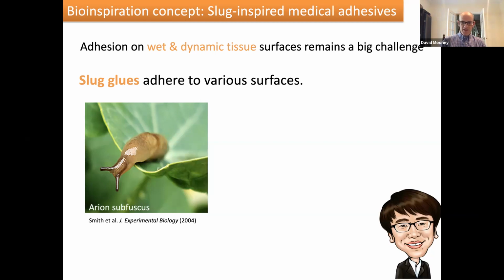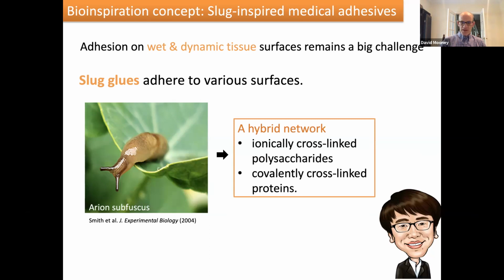And other scientists had characterized the composition of this mucus and found that it was a hybrid network comprised of both an ionically cross-linked polysaccharide network and a covalently cross-linked network of proteins. And Jianyu realized that this composition actually looked a lot like the composition that Shawnhee had earlier demonstrated gave this really significant toughening behavior to hydrogels in a broad sense. So Jianyu proposed to take that hydrogel system and use it as the basis for a new medical adhesive. The key feature that he needed, though, was a mechanism to enable that to adhere strongly and transfer stresses back and forth to the underlying tissue.